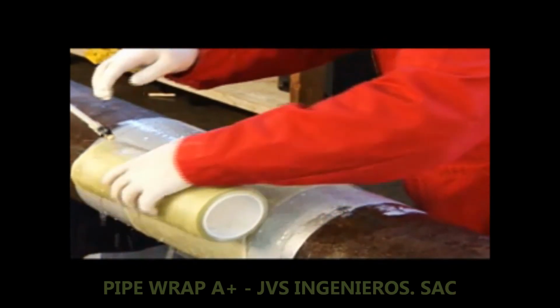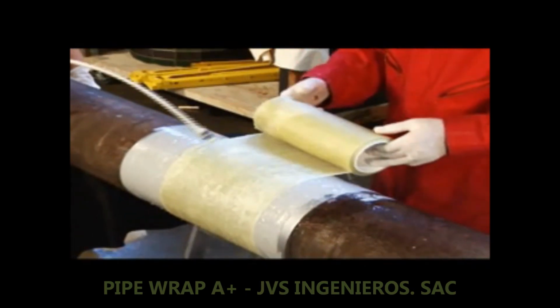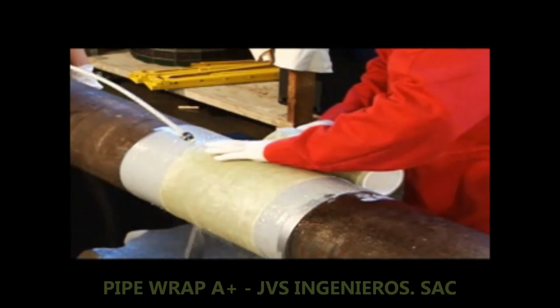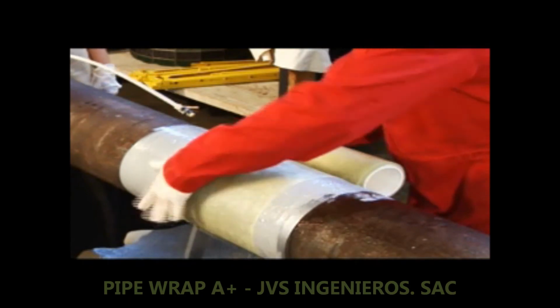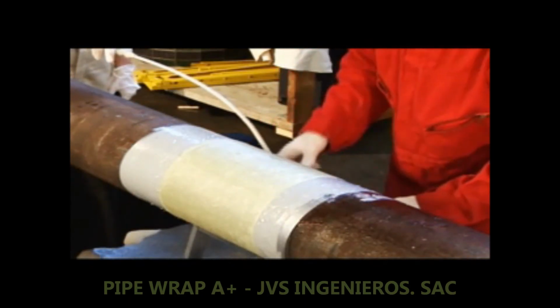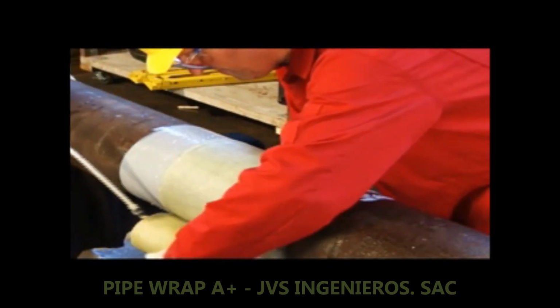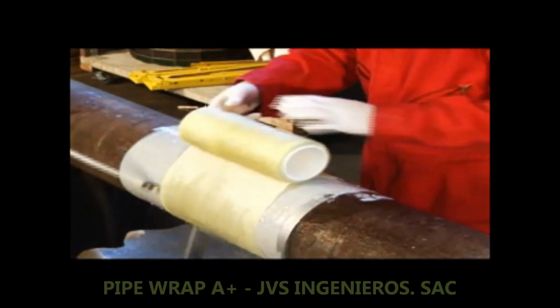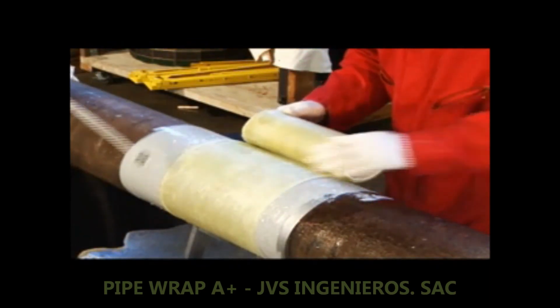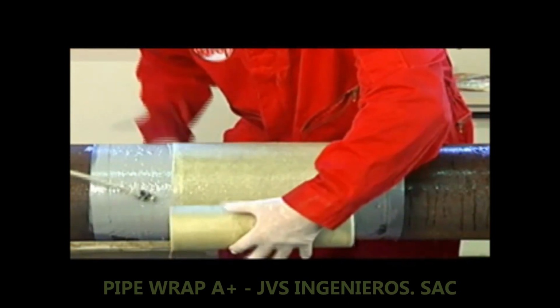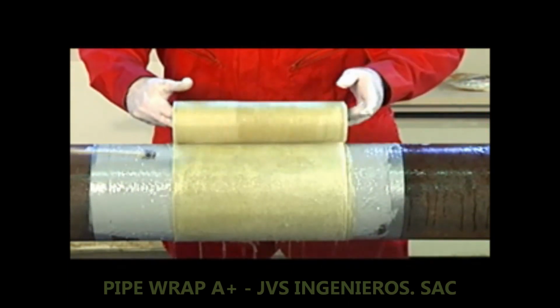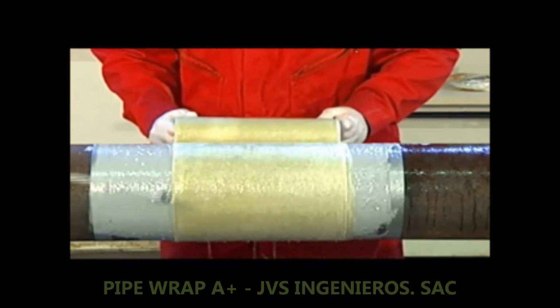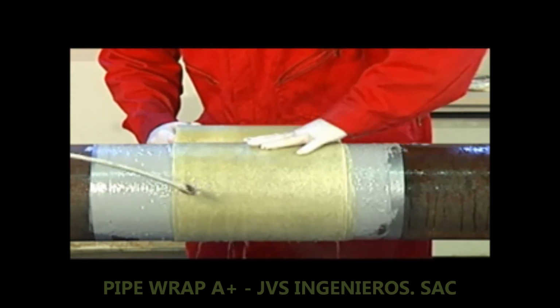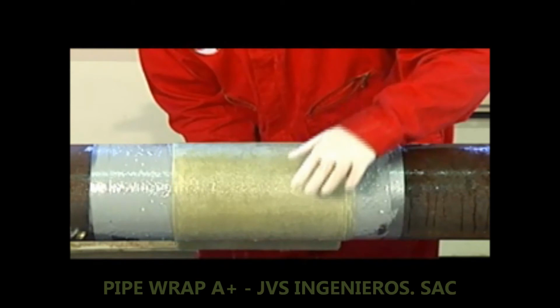Care must be taken at all times to ensure that all air spaces and voids are completely eliminated between the layers. Good adhesion between the layers is essential and can be accomplished with consistent pressing and firm smoothing of the layers with the open palm of the hand in the applied direction of the wrap. While wrapping, tiny droplets of water should be visibly squeezing through the weave of the Pipe Wrap A+ fabric, all 360 degrees around the pipe repair.